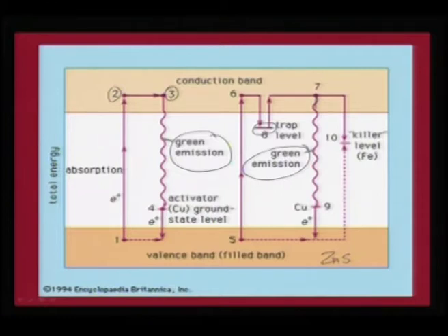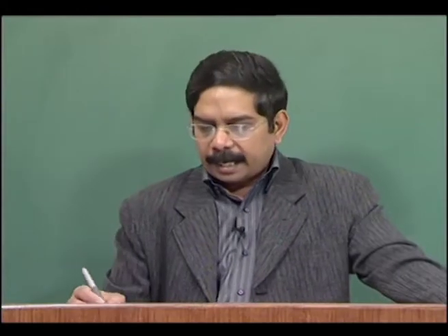If we have very little amount of iron that is coming out as an impurity, then this can actually act like a killer. So, this is called a killer level, because any other impurities which are in same comparable atomic level can actually bring about quenching of this light.